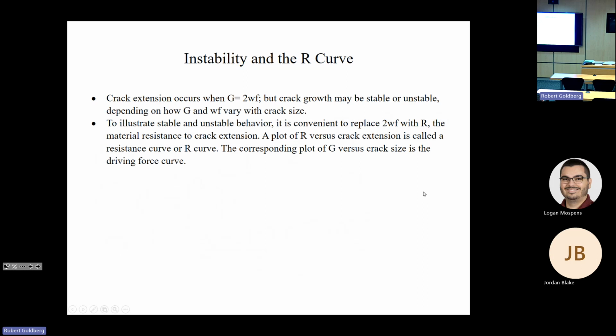Okay. So the next topic we're going to go into is instability and something called the R curve. So we knew when we talked about it that crack extension occurs when the strain energy release rate is 2 times the surface energy, but the crack growth can be stable or unstable depending on how the strain energy release rate and the surface energy vary with the crack size.